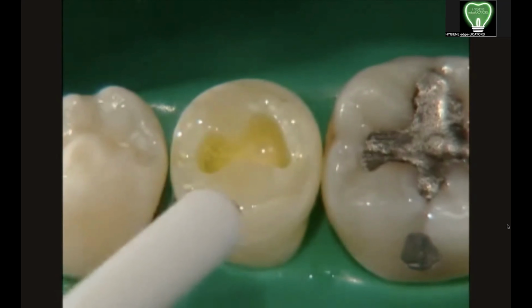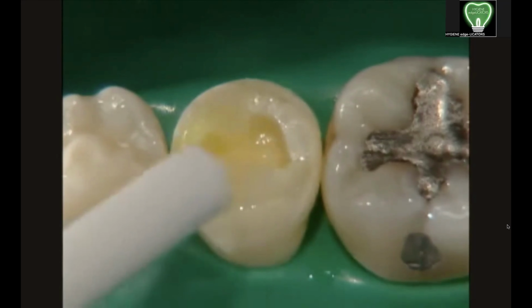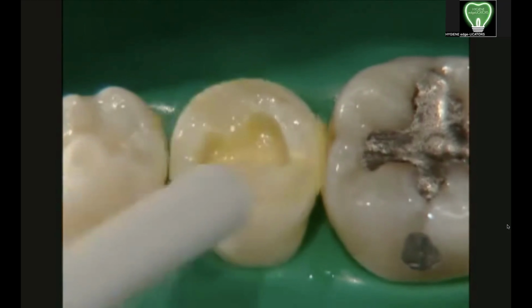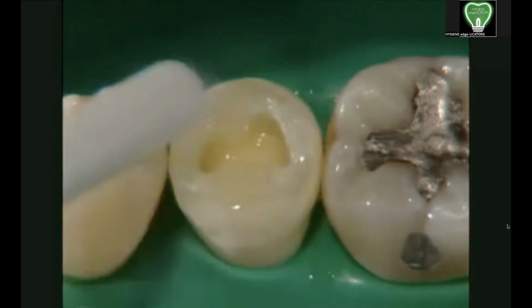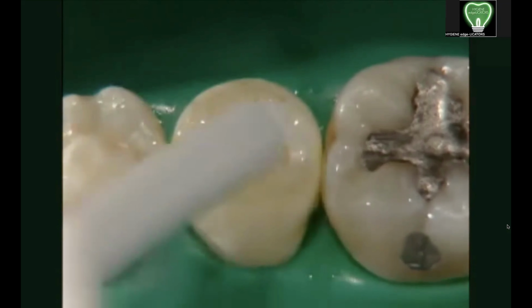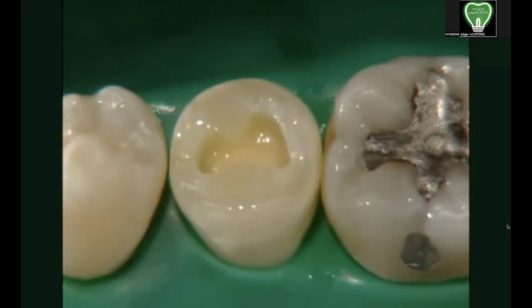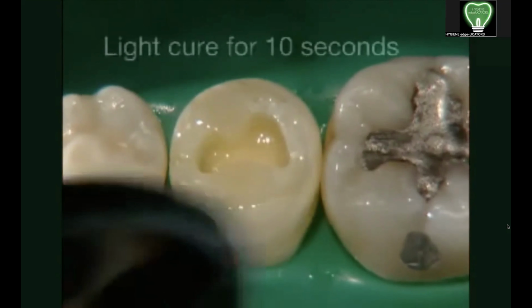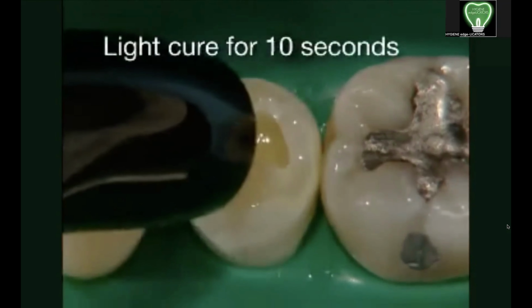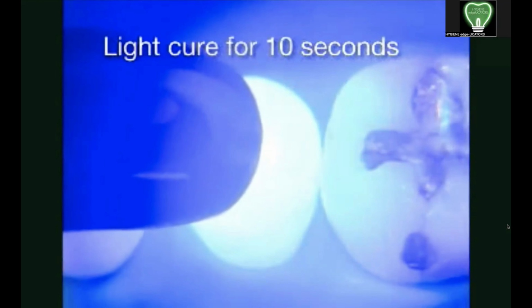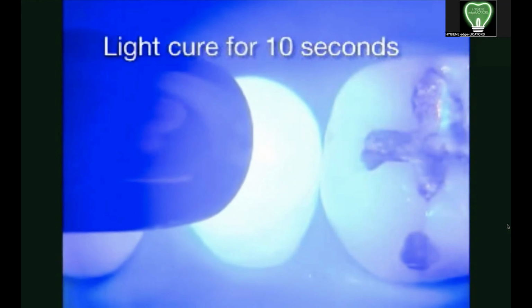Next, air thin the liquid for approximately 5 seconds until the film no longer moves, indicating complete vaporization of the solvent. Light cure for 10 seconds. The surface is now ready for composite placement.